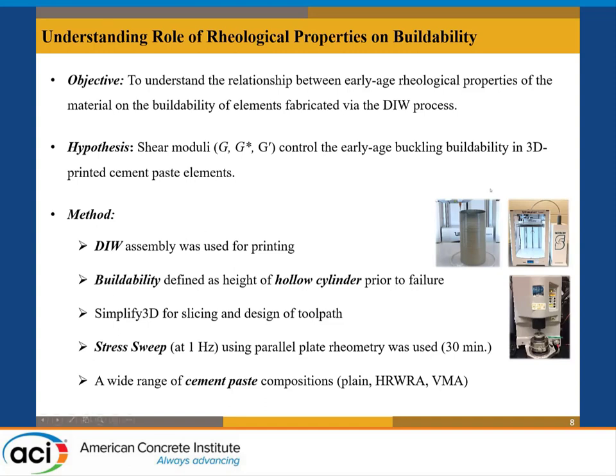The method we use is direct ink writing at a small scale to 3D print hollow elements, and we define buildability by the height of the hollow cylinder. We picked a hollow cylinder because it's one of the geometries most sensitive to buckling. We use a stress sweep from 0.1 Pascal to beyond the material's yield stress using a parallel plate within the same time frame at which printing was being conducted. We use a wide range of mixtures to diversify the range of rheological properties, while also ensuring we could print and build in order to study the system.